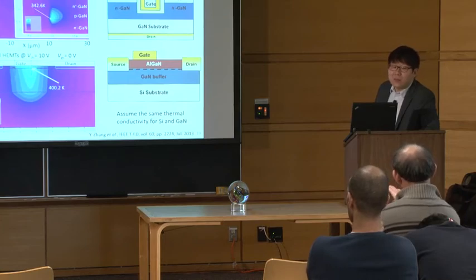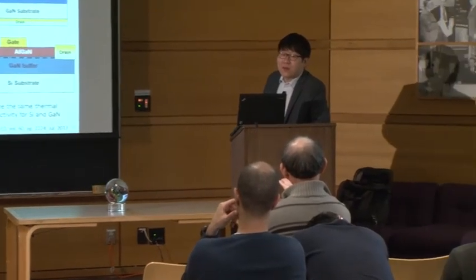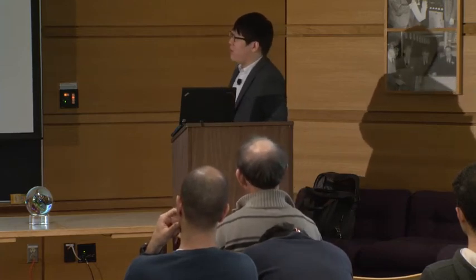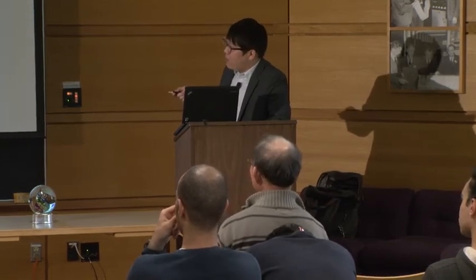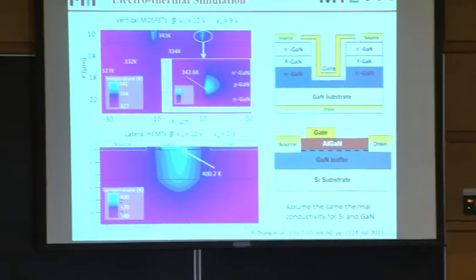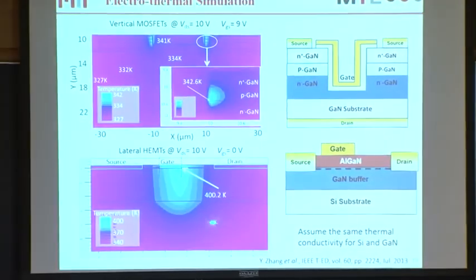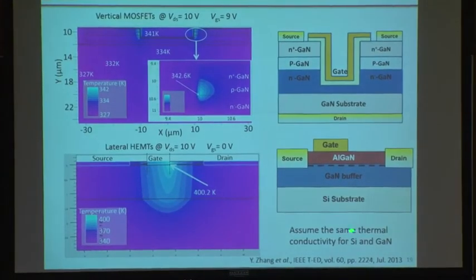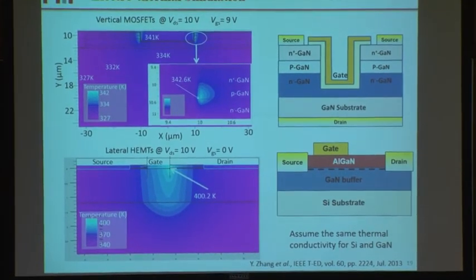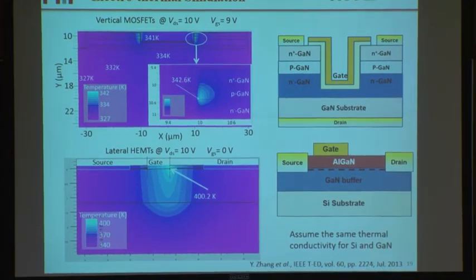So if we flip it, using a heat sink on the top as opposed to the bottom, I guess the distribution of heat will be different. I think it would be very interesting to look at. Another thing is that in real applications, people will thin down the substrate to bring heat extraction closer to the channel region. Typically for GaN-on-silicon lateral devices, they will thin down the silicon substrate to tens of microns.